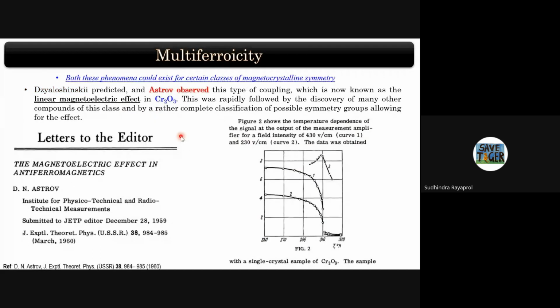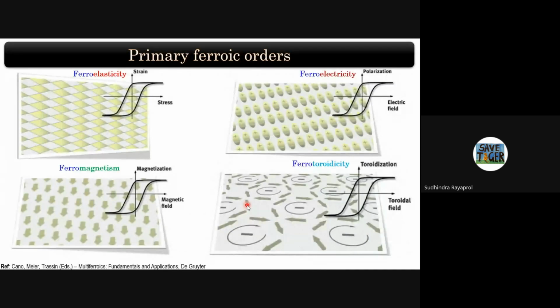And this was experimentally shown in Cr2O3, Astrov showed that there can be a coexistence of ferromagnetic and ferroelectric coupling. But the problem is that you can have a ferroelectric part and a ferromagnetic part in one sample, in one phase, but whether there will be a coupling between these two. And this was the basis of what are known as multiferroic systems.